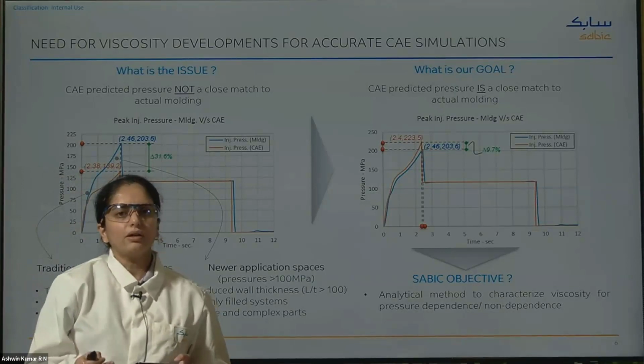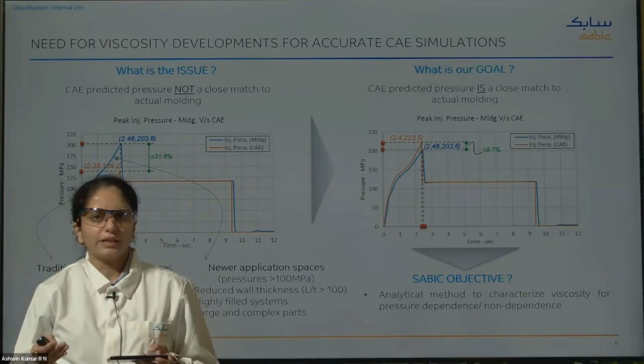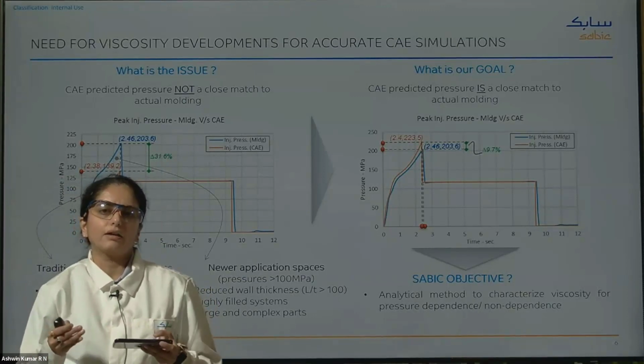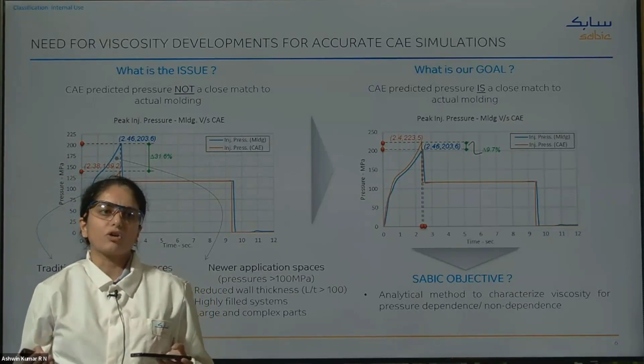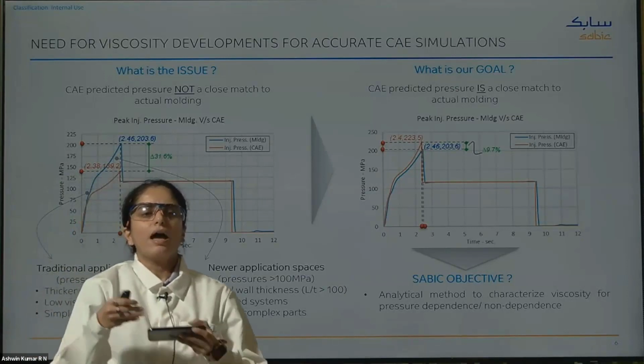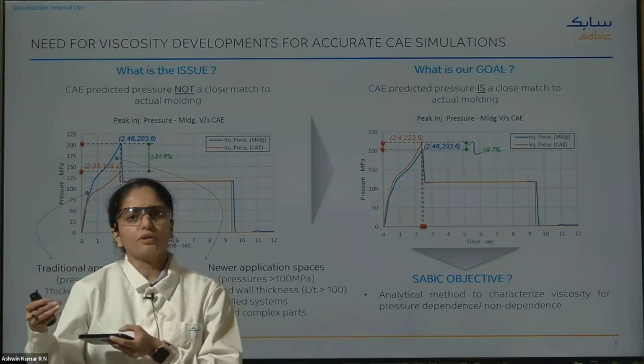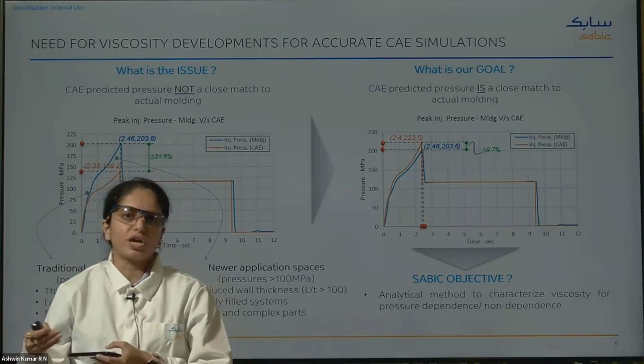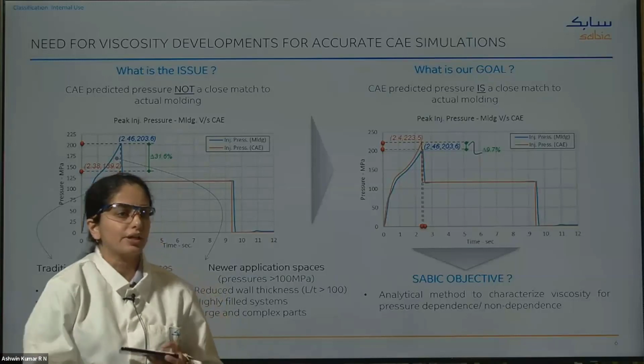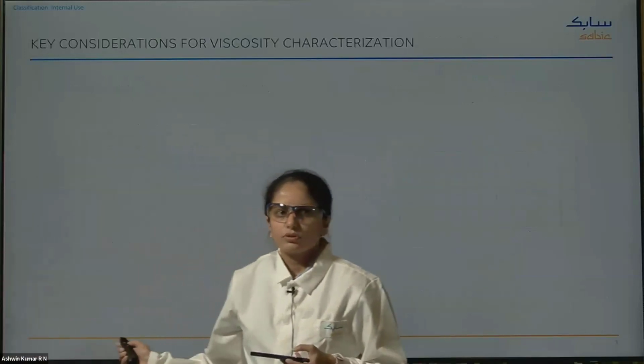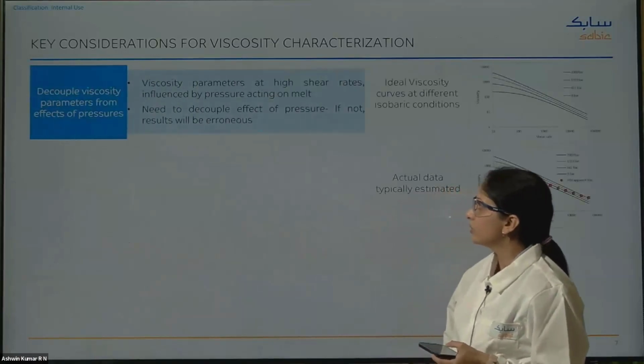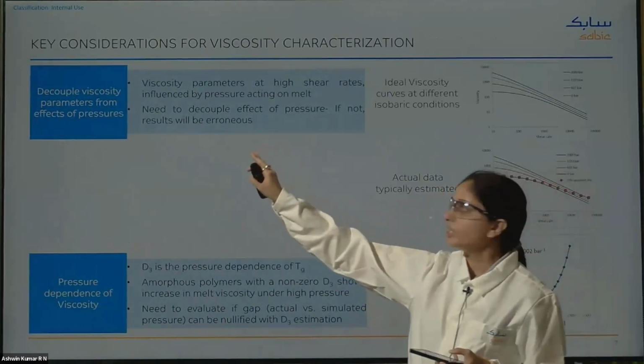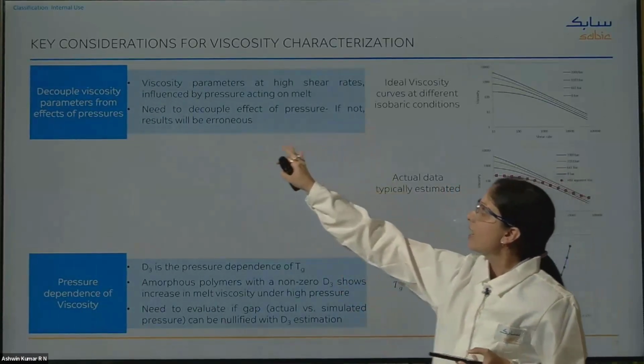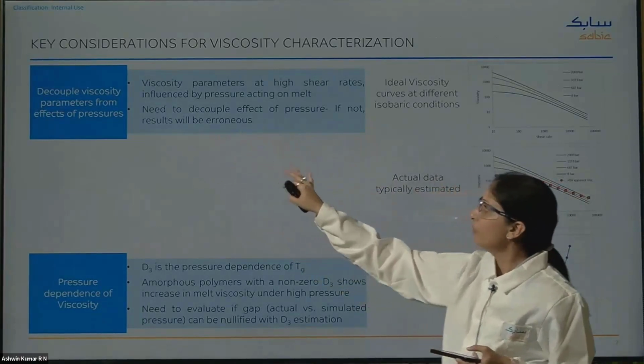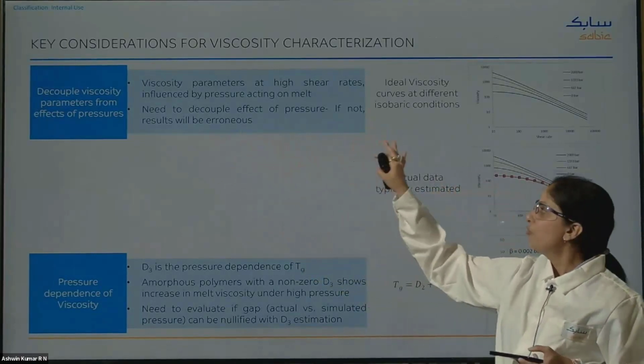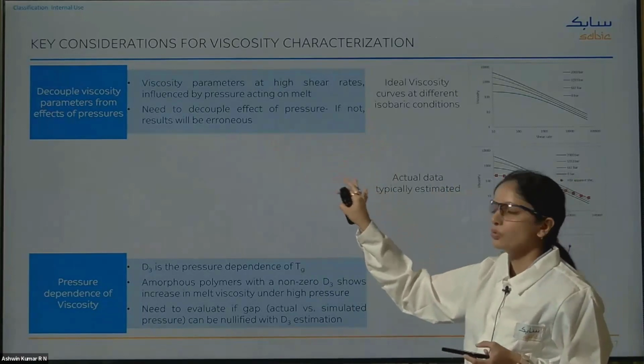So in the current method where we measure the D3 parameter, the effect is a convoluted effect of pressure as well as of the high shear rates which are encountered inside the capillary rheometer instrument. I'll talk about what exactly we are doing. Viscosity parameters at high shear rates are influenced by pressure, and we need to decouple the effects of pressure. If not, the results will be erroneous.